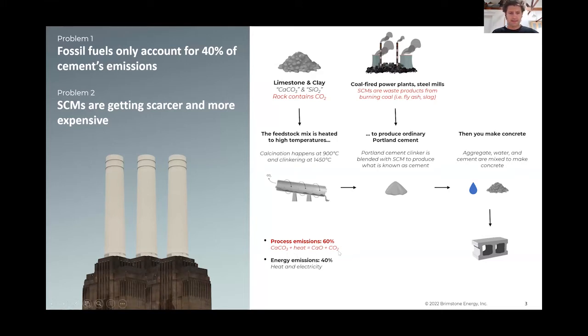And that's because these CO2 emissions have nothing to do with a fossil fuel. They have to do with the chemistry of making the product. So the CO2 is embedded in the rock, and when you heat that rock up, you release the CO2 into the atmosphere in order to make calcium oxide. So another way to say that is, if we were to use 100% clean energy with the conventional way to make Portland cement, about 60% of the CO2 emissions would persist.